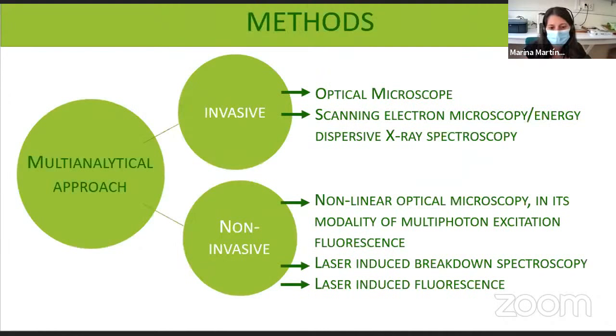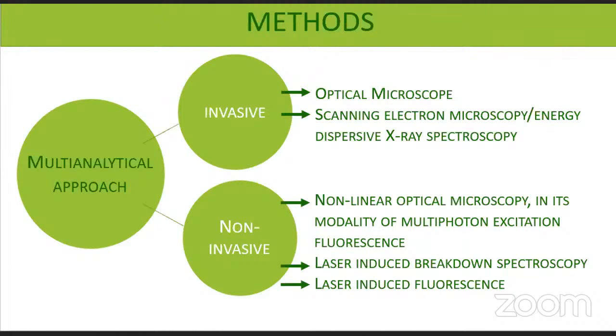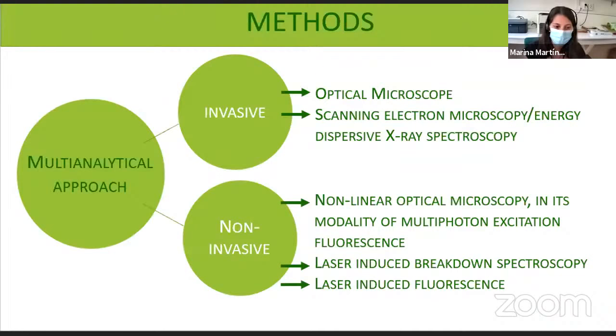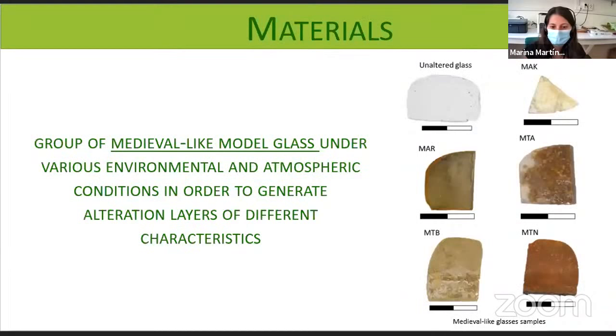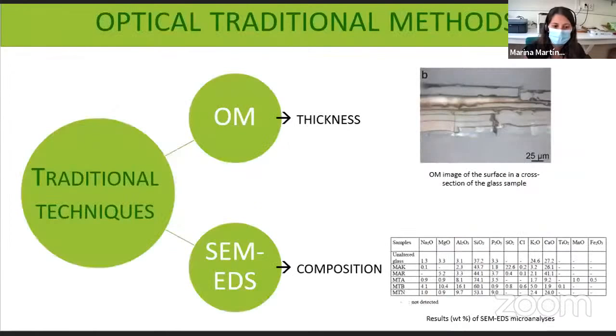In order to determine the effectiveness of the laser techniques, we perform a multi-analytical approach to the sample through the comparison of two sets of techniques, the traditional and invasive techniques and the non-invasive ones. The samples are a group of medieval-like model glass under various environmental and atmospheric conditions in order to generate alteration layers of different characteristics. To study the multi-layer structure and composition, traditional techniques include the use of cross-section to gain access to the inner part of the glass body. The surface and stratigraphy of the glass samples was studied by optical microscope, and their chemical composition was determined by scanning electron microscopy energy dispersive X-ray spectroscopy, SEM-EDS.